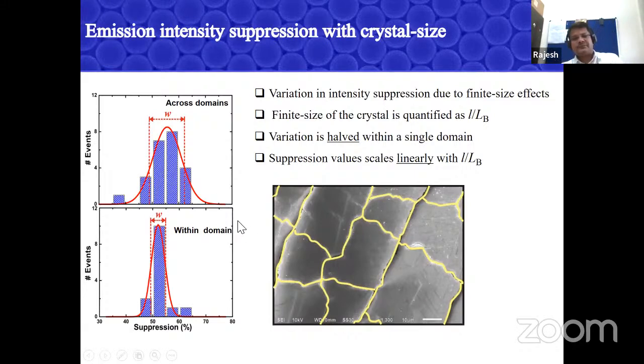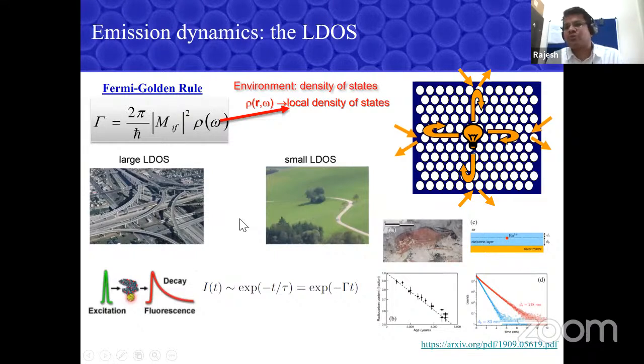So the other thing is that I've shown you that the emission intensity is changed. But does it clearly say that the density of states is changed or reduced within the band gap? The answer is no, because emission intensity won't tell you whether there is a density of states change or not. It's simply a filter. If I increase the pump power, it still increases the emission or decreases the emission. That does not mean that the density of states changes. So what we need is to measure the decay rate. Okay, and the decay rate is related to the LDOS.